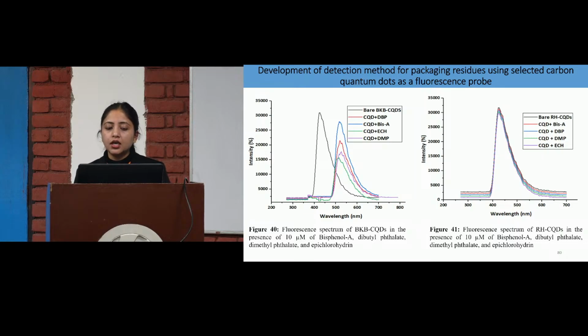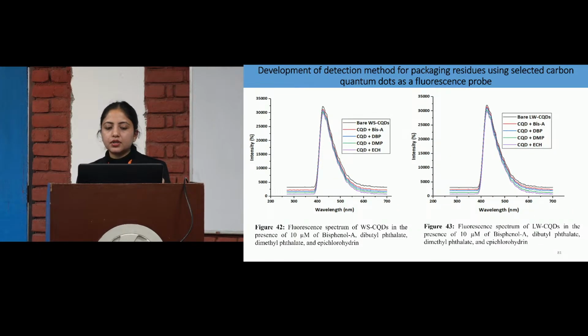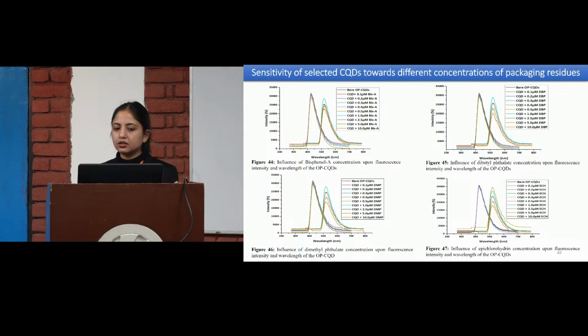Then that is the fluorescence spectra of the rice husk carbon dots. As you can see, there is a shift in the wavelength in the broken kidney bean, but in the case of the rice husk there is no shift in the wavelength. As we said earlier, the quantum yield of those samples is higher, and for the rice husk and liquid whey the quantum yield is less, or there is less carbon content. So they do not interact or bind with the analytes. So they do not shift any wavelength or intensity. So they were not selected. We selected only the onion peel, broken bean and the papaya peels for the detection purpose.